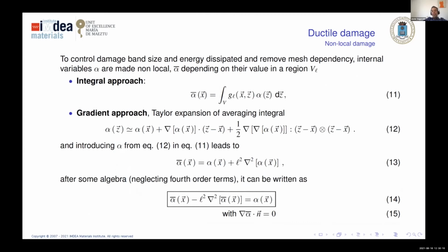So what is the idea? The idea is that some internal variable, which can be the volume fraction of porosity or another variable, does not depend on its own value, so it is not local, but depends on some surrounding points. The non-local version of the internal variable, imagine the porosity, is just the integral of some weighting function times the value of the local counterpart in a region controlled by a characteristic length.